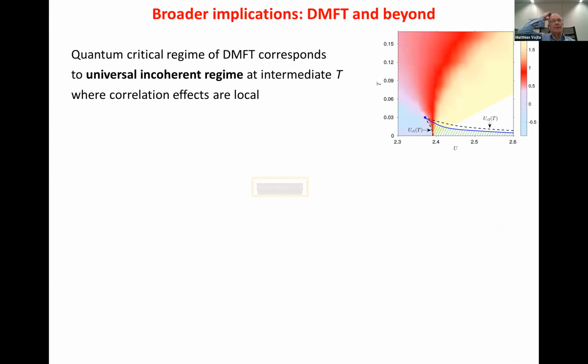So let me discuss this. First of all, the regime where this critical scaling appears is fully incoherent. If you look at the spectral functions I've just shown you, there's no quasi-particle whatsoever. This regime is dominated by strongly incoherent, or strongly inelastic, scattering. So we have a universally incoherent regime at intermediate temperatures.